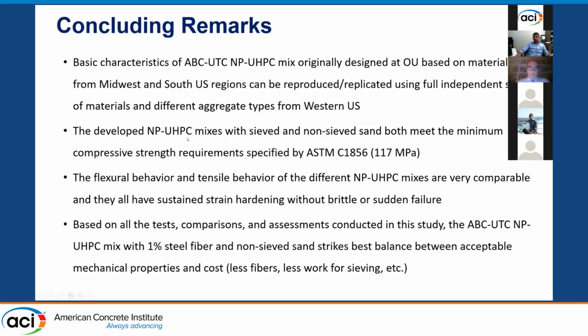The developed non-proprietary UHPC with sieved and non-sieved sand both met the minimum compression strength requirement of 117 megapascal, the very lower end that we were targeting. Flow and tensile properties were all met. So having an unsieved sand is not really bad. We know for sure that this is not ideal in terms of optimal particle packing, but at least for practical purposes, we showed that it works. The flexure and tensile behavior both showed all the trends that we are looking for: the initial strain hardening, and then the ductile behavior.